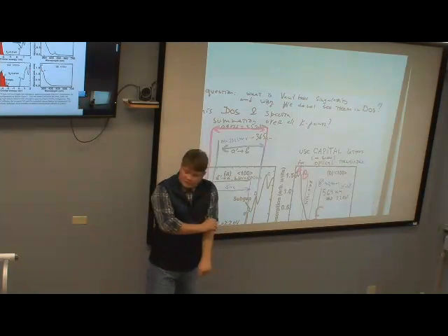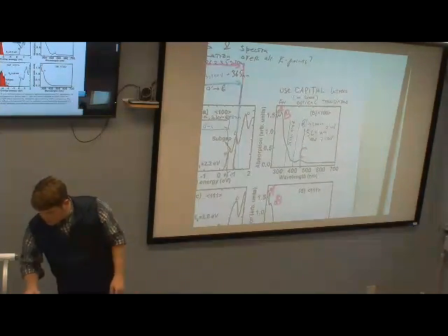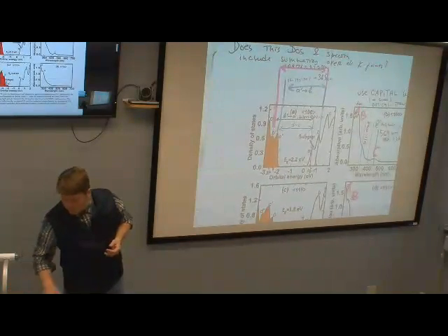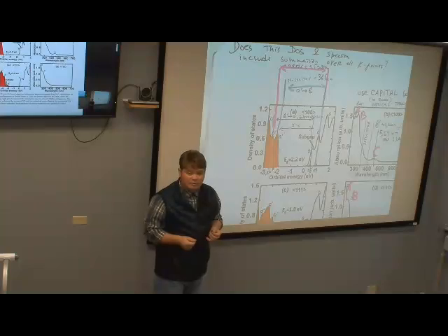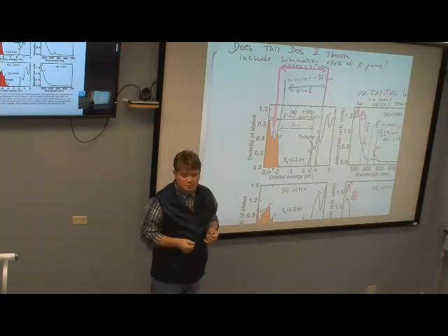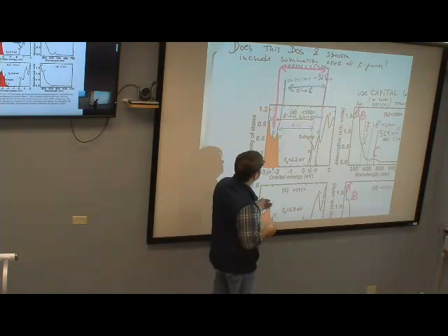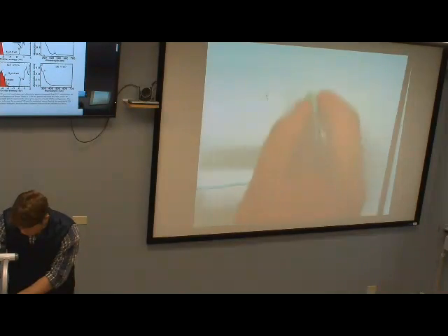Another thing that I would ask as a reviewer: for one-dimensional structures, one often expects to see so-called Van Hove singularities. So the DOS for one-dimensional structures is expected to approximately show these features.